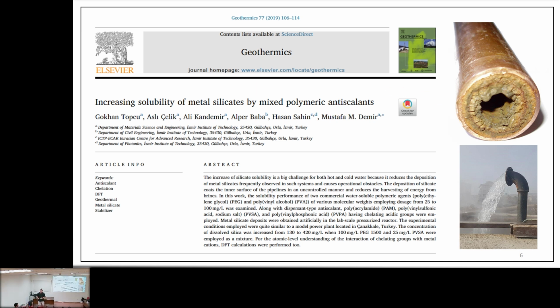Then we performed some very, very simple calculations, just binding energy of a molecule on a surface. We calculated some molecules, and I suggested that PEG, PVA, PAM, and PVPA can be good for removal of such metal silicate. And then they performed some experiments by using some mixtures of those things.